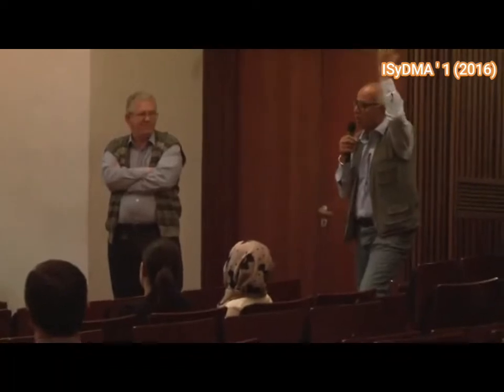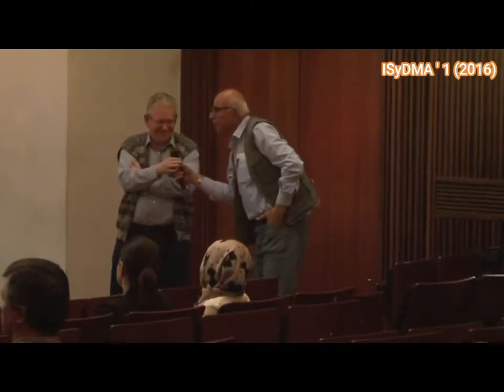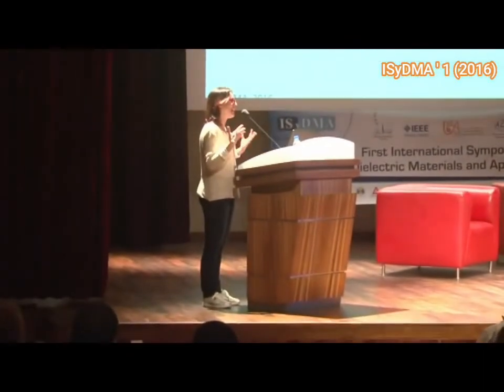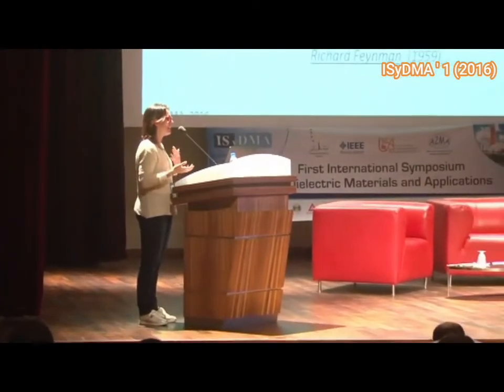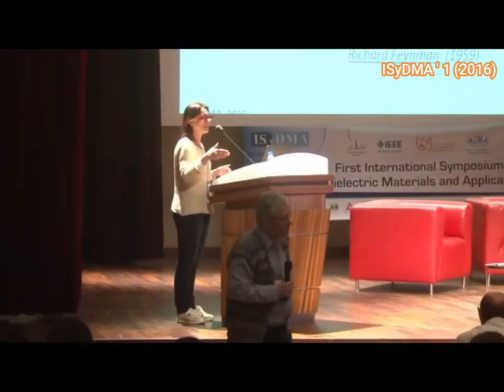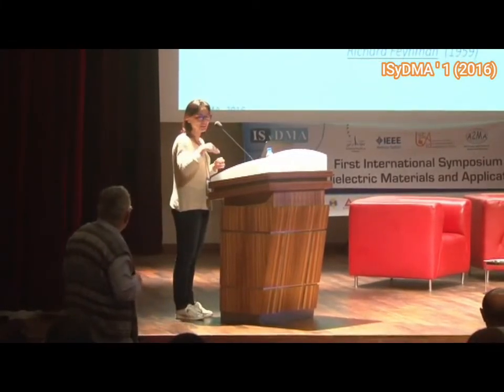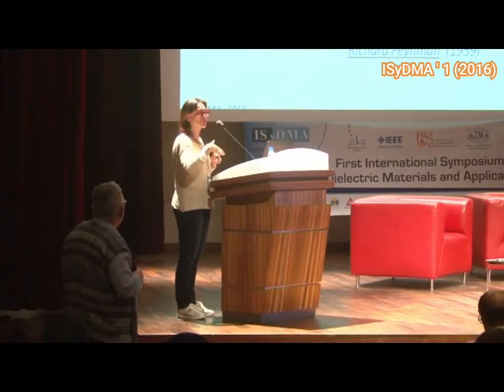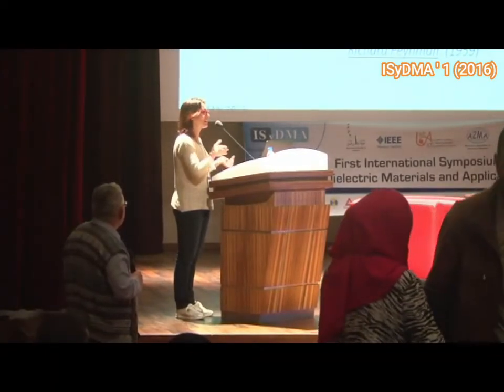Just like the Egyptians 4,000 years ago, yes, sure. They did the same technology. We know quite well that this decorated pottery, or the glass, just incorporating cadmium selenide or cadmium sulfide, changes color with the temperature treatment, moving from yellow to red, just changing the temperature. You don't need luminescence. And also the presence of a passivating external layer can be not good for charge transport. So in that case, you use just the core of cadmium selenide.